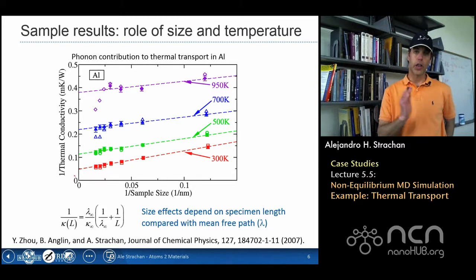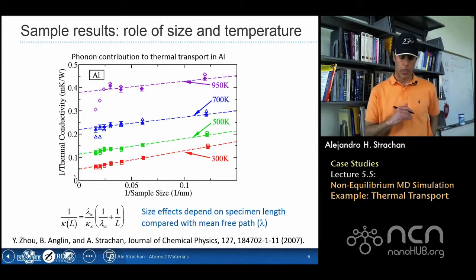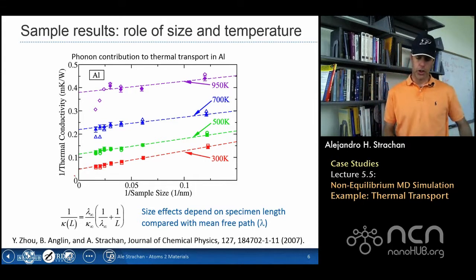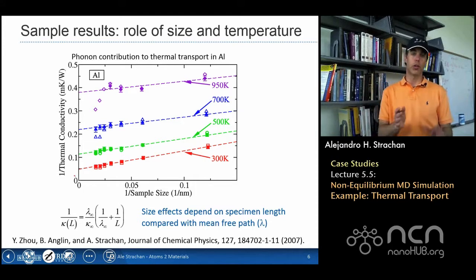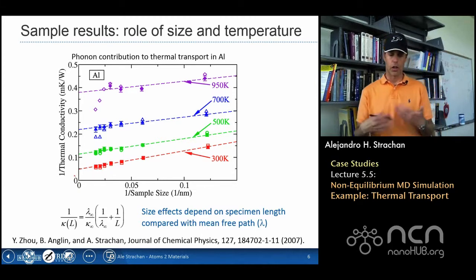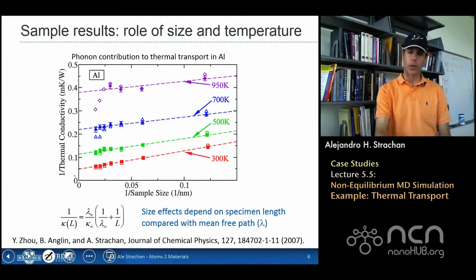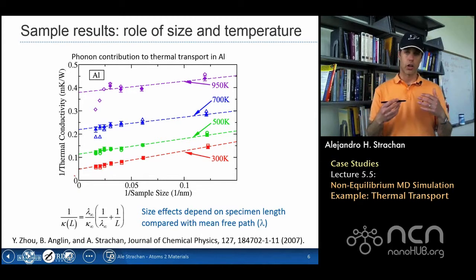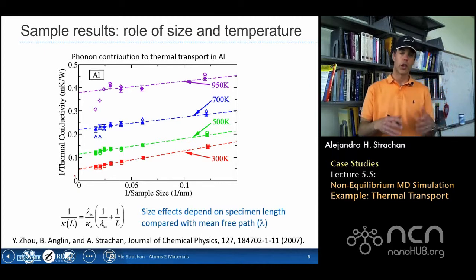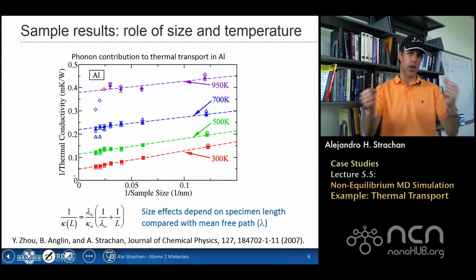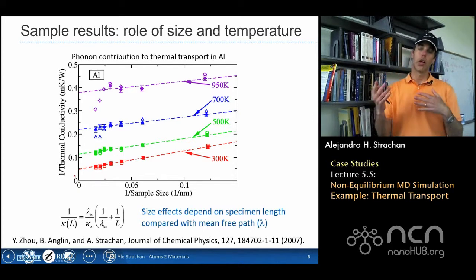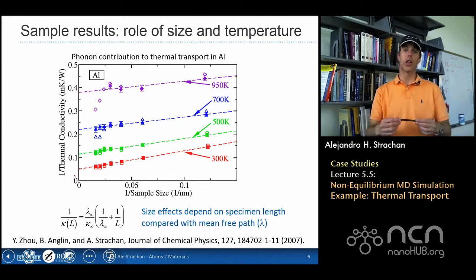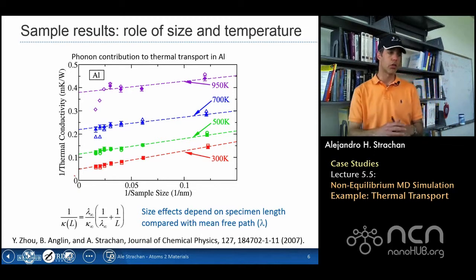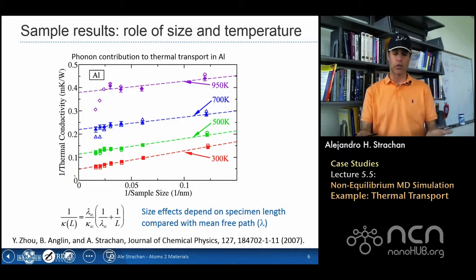These are results where we show the inverse thermal conductivity as a function of inverse sample size and at different temperatures, okay? What you see here is this linear relationship between inverse thermal conductivity and inverse sample size for all of these temperatures. So the first thing you see is that at higher temperatures, the thermal conductivity goes down, okay? The inverse thermal conductivity goes up. And that's, of course, because of increased scattering due to more anharmonicities. The higher the temperature, the more anharmonic the system is, and the more scattering mechanisms that you have. So MD captures that explicitly. There is no knob to turn. There's nothing. The simulation just predicts that on its own. Of course, with the limitations of the interatomic potential.